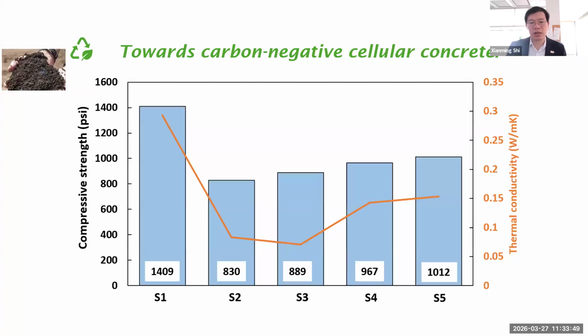So as you can see here, when you're foaming it up and add so much biochar, 30%, of course, you're gonna lose some of the strength, but they're still sufficient to serve as cellular concrete, because usually these are not used as structural concrete. They're used as separators or sound insulation, thermal insulation, and fire resistance, because these properties are built in because of the built-in porosity of the pores you saw in the biochar.